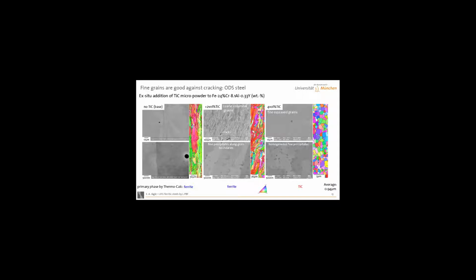At first, you generate cracks, which is not very nice, of course. And you find a lot of precipitates along grain boundaries, presumably titanium carbide or some other carbides, I don't know. But if you add enough titanium carbide, in this case 4 volume percent TiC, you go to a very nice fine-grained, sub 1 micron grain size equiaxed microstructure. You have tons of these fine precipitates, and you don't have any cracking problem anymore. So on one slide, I have managed to tie together 2 of previous talks from this morning and this afternoon.